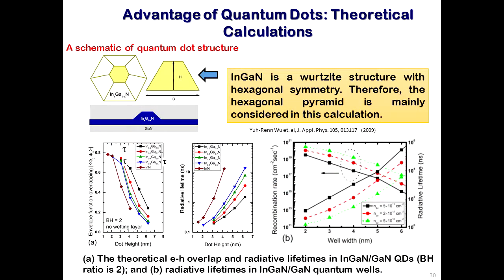What got me interested was these theoretical calculations, which were done by one of my colleagues. One of the problems in the LED world with the quantum wells, all the quantum wells that are made and sold and commercialized, is that the LEDs have quantum wells in the active region as the emitters. The one problem is that their lifetimes are very, very long. So by the time a radiative recombination can take place to give out light, more often than not, the carriers go to non-radiative centers and are lost as phonons or heat.